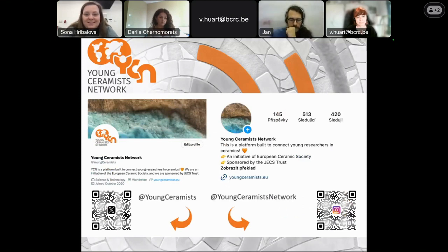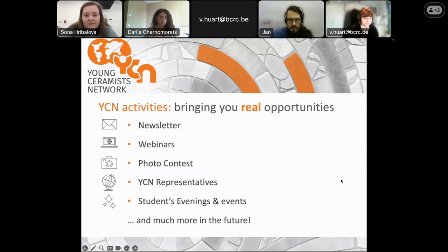If it was that easy, we'd have a lot of transparent ceramics, because we also have scattering, and scattering is the one that's really inherent to ceramics because it depends on the microstructure. It really depends on how your material was made, not as much on its chemical or phase composition.